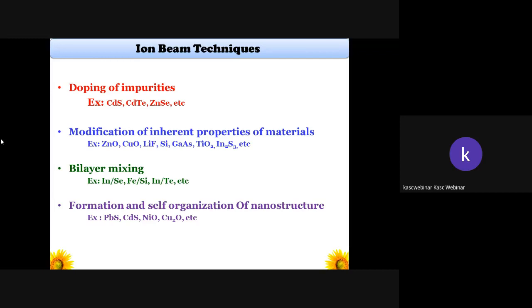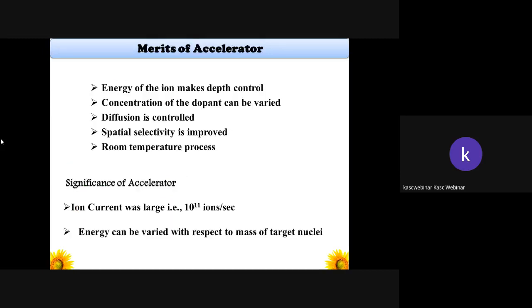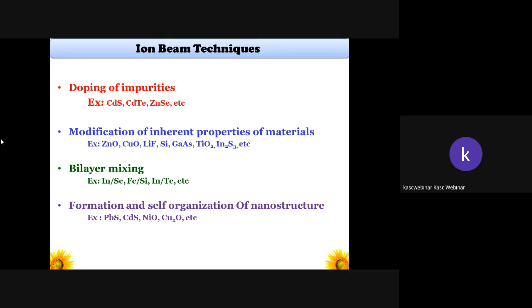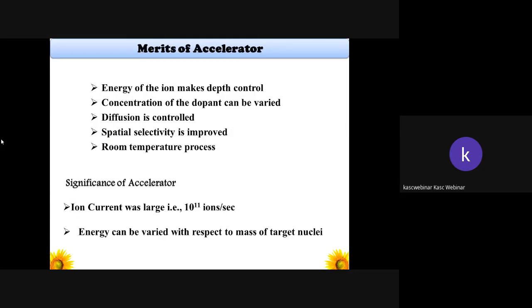For example, cadmium sulfide, cadmium telluride, zinc telluride, zinc selenide, and so on. Then the modification of inherent properties of a material itself, and the bilayer mixing in the case of iron silicide sample, indium selenide and indium telluride, and the formation of self-organized nanostructures. And the instrumentation which we have used for ion beam techniques is the accelerator technique, especially the particle accelerator or a linear accelerator called a Pelletron accelerator.